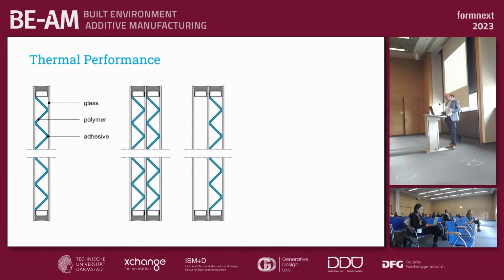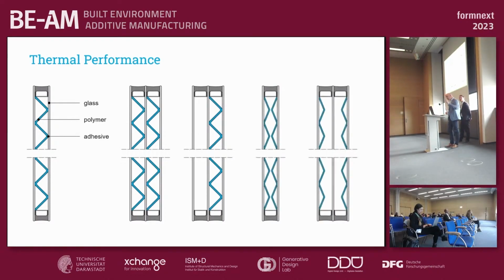I cannot point with this computer, but the idea is perhaps to apply a second layer, as you also see now with triple IGU, triple insulating glass, and make sure that the cores in these two individual chambers don't touch, so that you don't have direct conduction there. Or simply apply an extra layer with a cavity which is empty, which can still benefit from the stiffness of the other panel. But in this case, you avoid this thermal bridge from inside to outside. And the other option is to separate the core, to make two cores, to print them on either side of the glass panel, so that you avoid that this core is bridging from the one glass to the other.